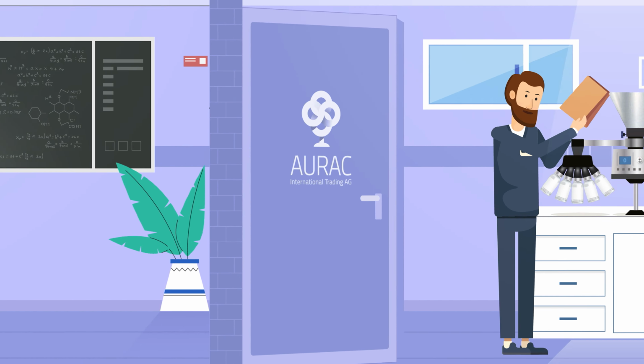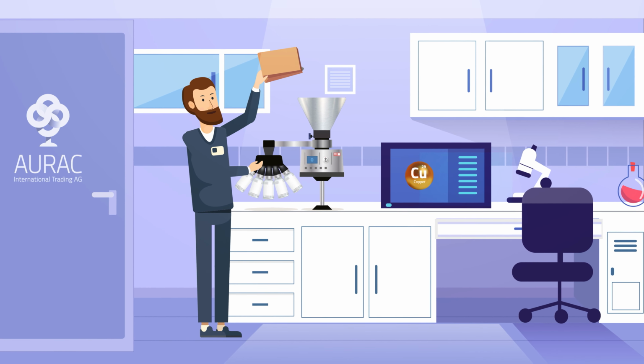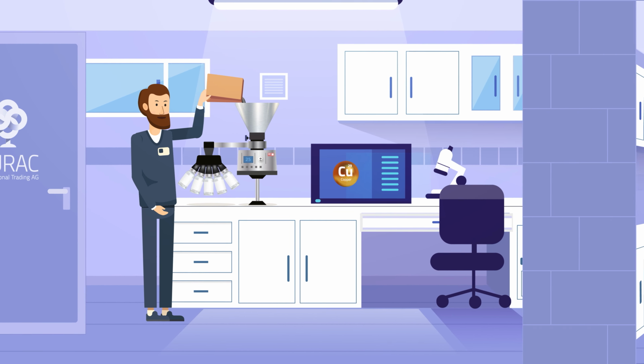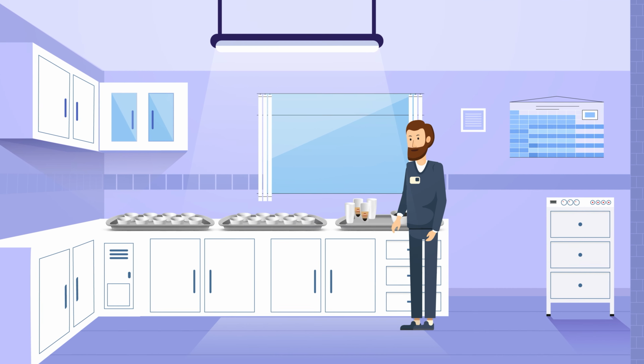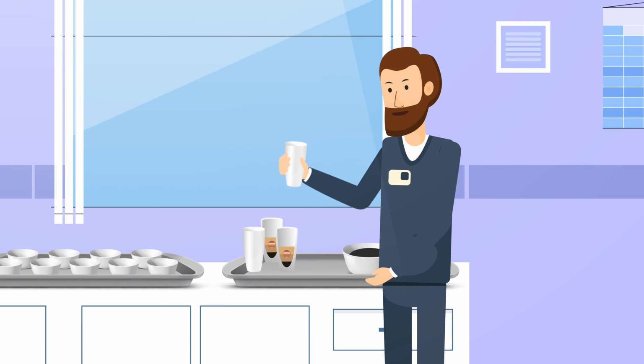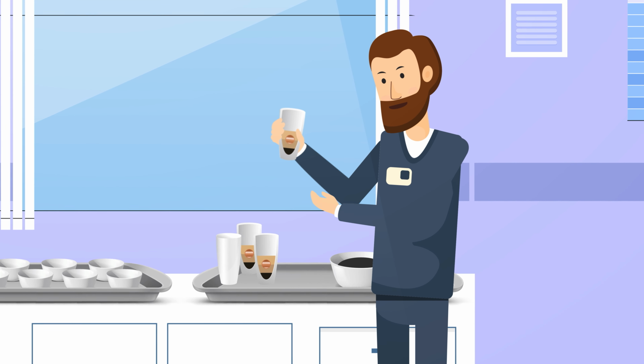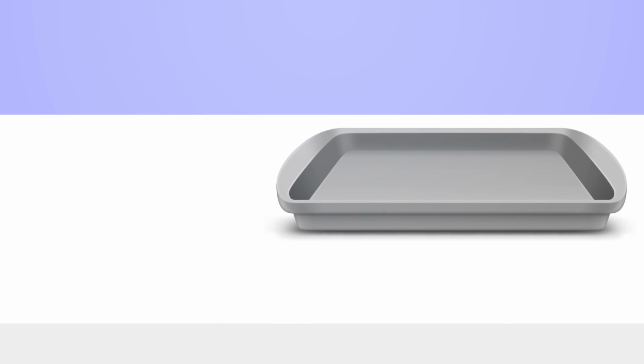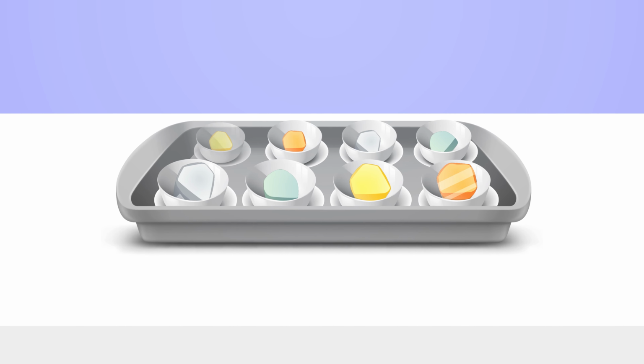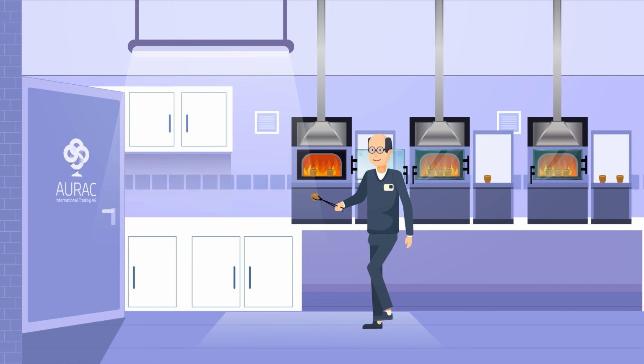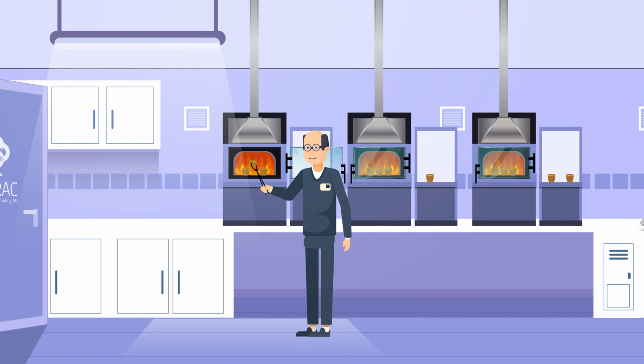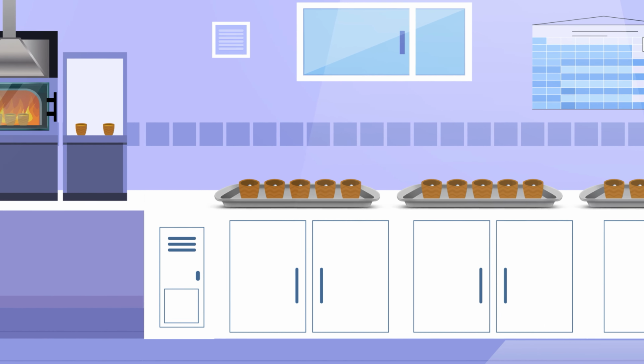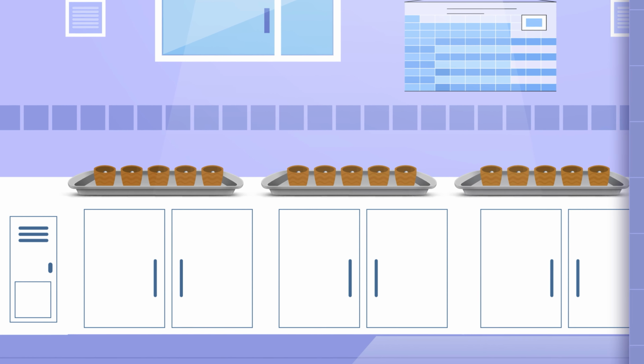These samples are thoroughly analyzed to determine the concentration of precious metals. The slag, a byproduct of the melting process, contains no precious metals and is discarded as waste. The material is processed again in the second melting, and a small metal bead forms. A porous clay crucible absorbs the base metals, leaving behind a precious metal grain containing silver and gold.